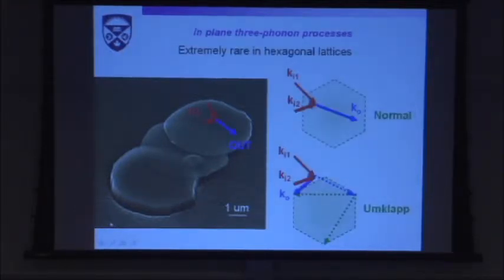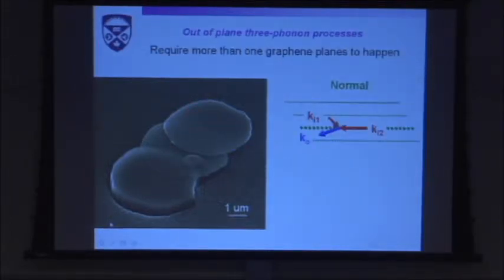So you have to go to the fourth or the fifth order, collisions of 4 or 5 phonons, to bring incoherence to these lattice vibrations and limit the thermal conductivity. That's why it's so great. But look at what's going on if you don't have one layer of graphene. You can have out-of-plane phonons.